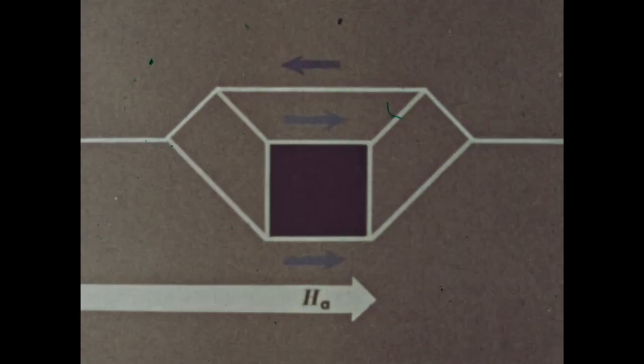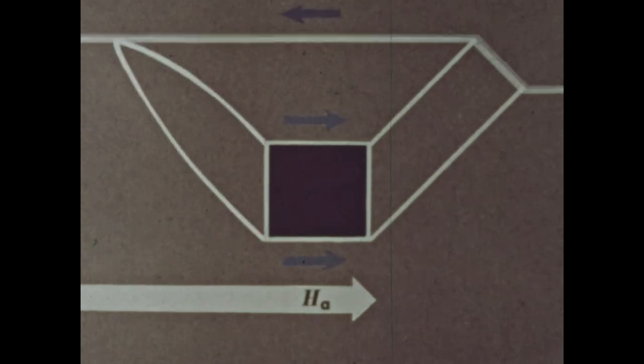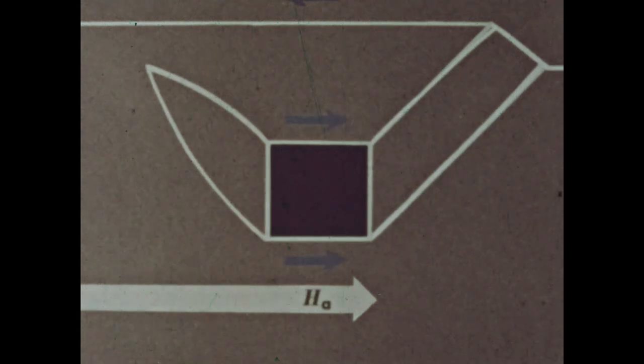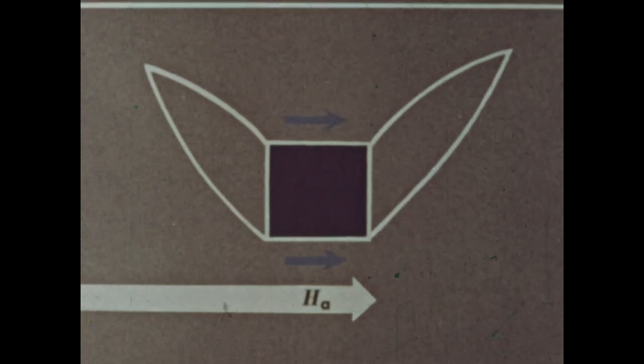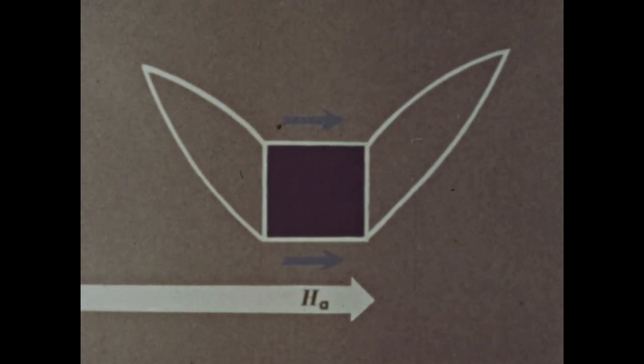Finally, however, it breaks loose and another spike forms and shrinks. Notice that even if the primary domain wall is moved very slowly, when a spike forms, energy is lost, which cannot be regained. Thus, this is an irreversible process.